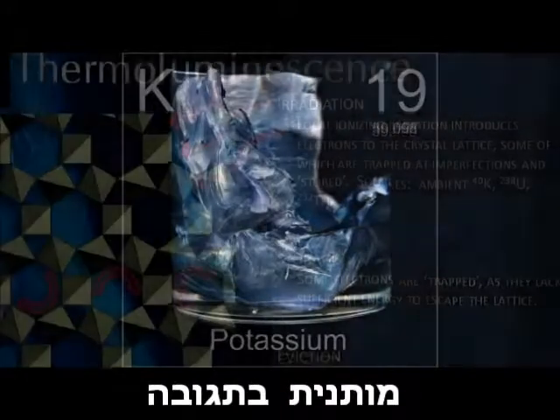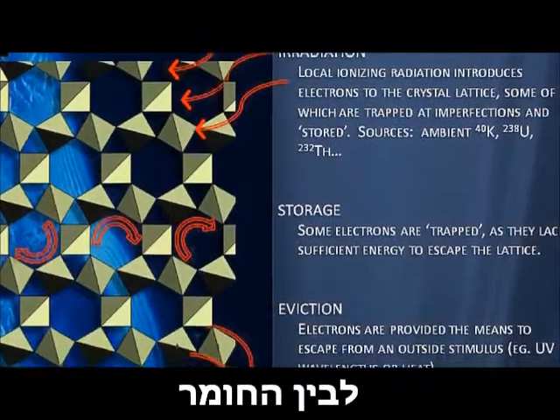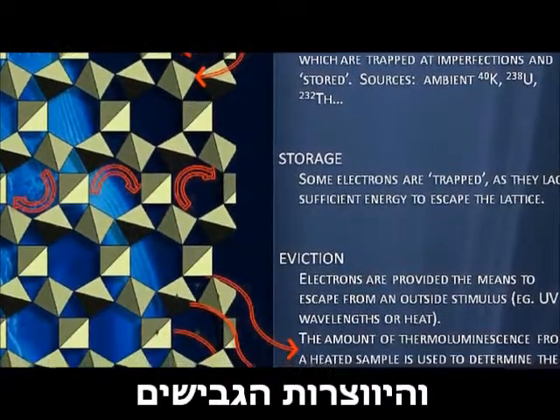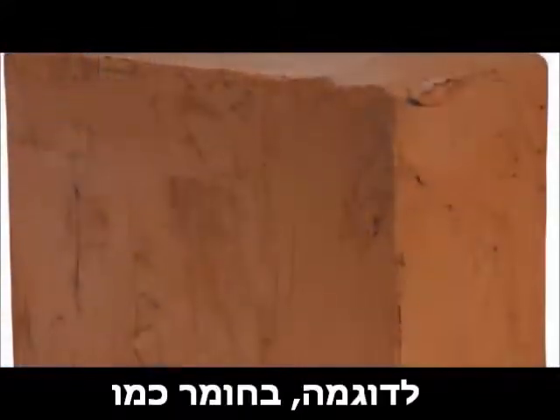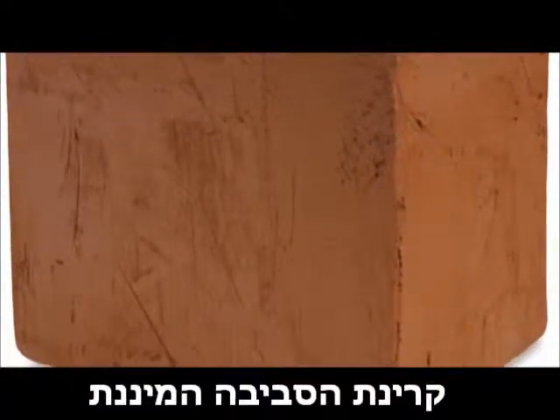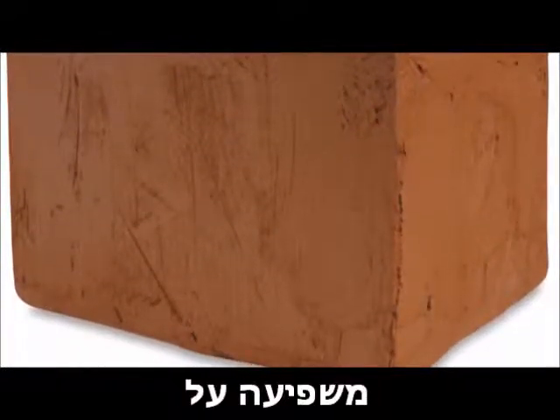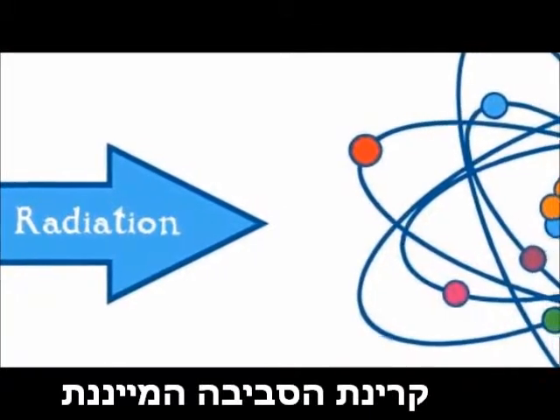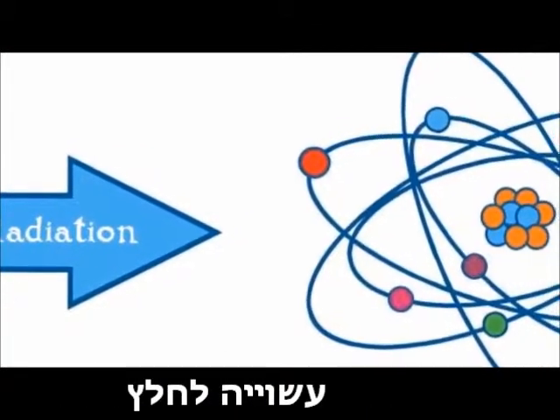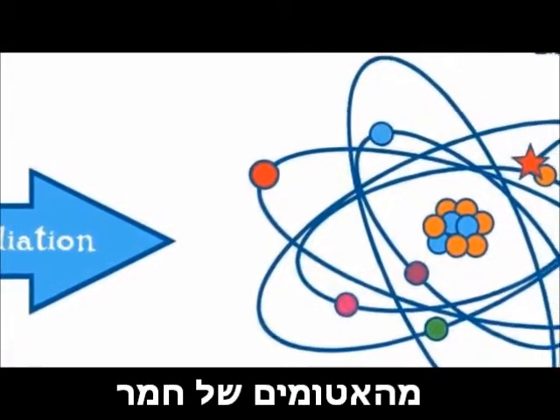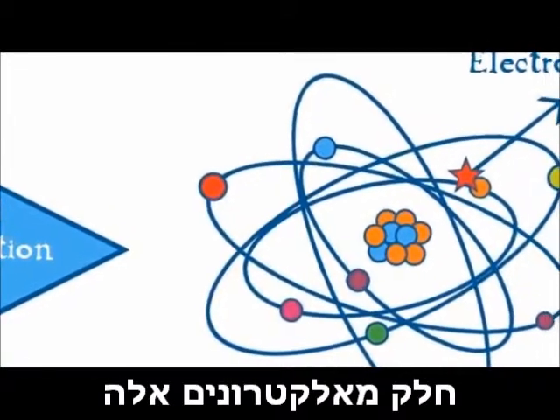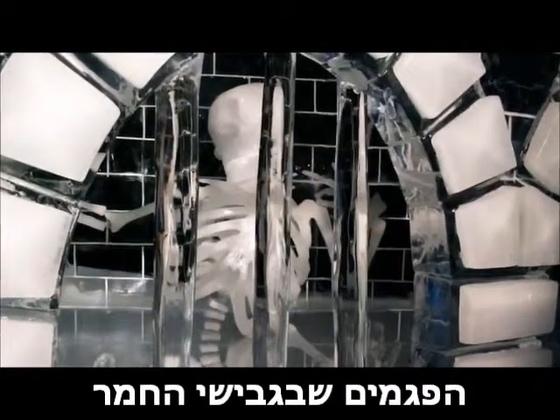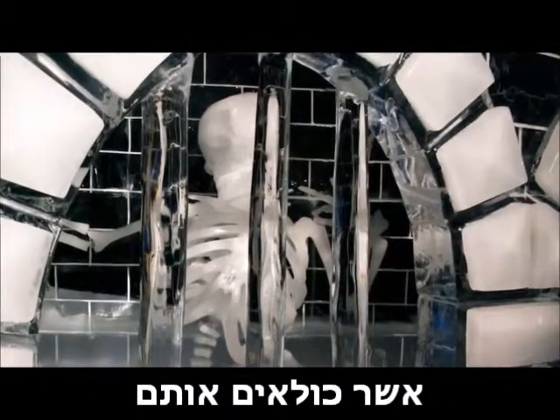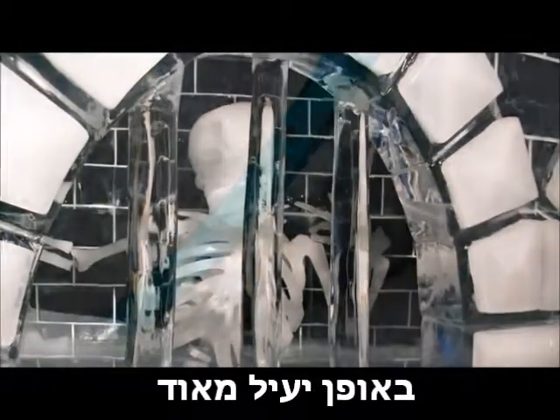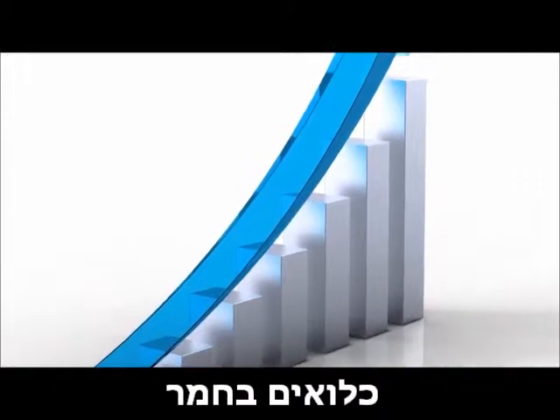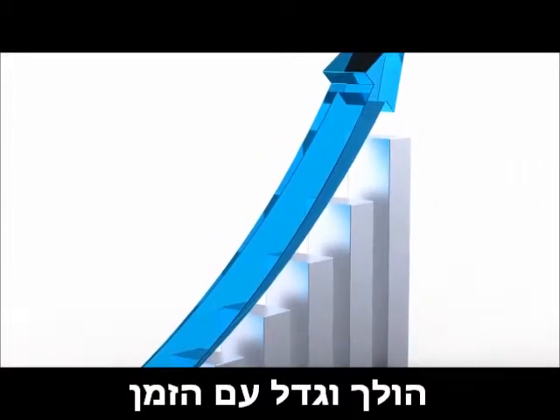Thermoluminescent dating depends upon a reaction between this radiation, certain materials, and crystalline formations. For example, in a material such as a block of clay, background radiation will have an effect upon its atoms. Ionizing radiation has the potential to dislodge and expel electrons from atoms within the block of clay. Some of these electrons are then caught within crystalline imperfections within the block of clay, effectively imprisoning them. The number of electrons imprisoned within the clay will continue to rise through time.